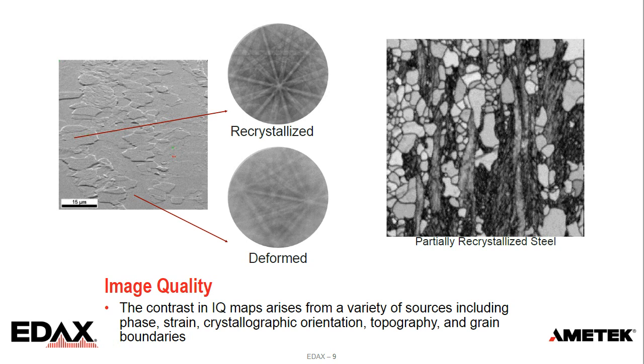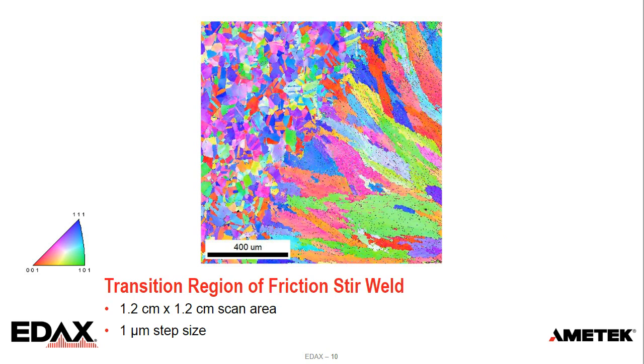This is the orientation map of the transition region of that weld. So we can see on the top left the transition zone and the base microstructure, a lot more polygonal grains with some twin boundaries in there. On the bottom right, we see the weld, where we see much more elongated grain shape, and we'll investigate that a little bit further. But we can get quite a bit of detail with EBSD, and this is a single field scan of about a centimeter squared with a 1 micron step size.